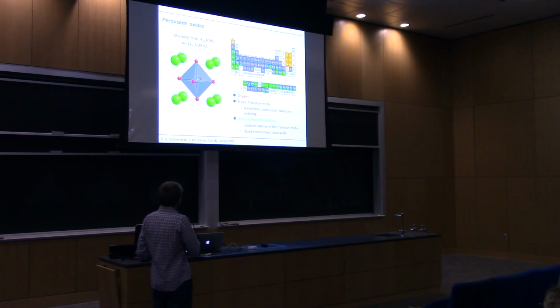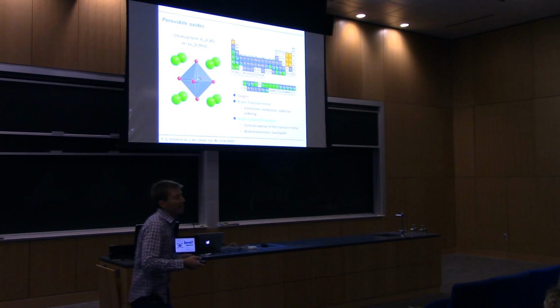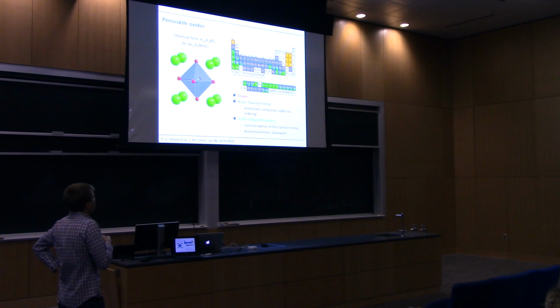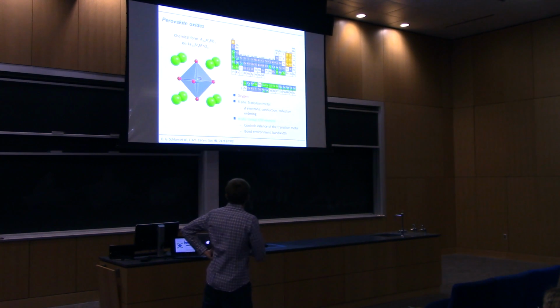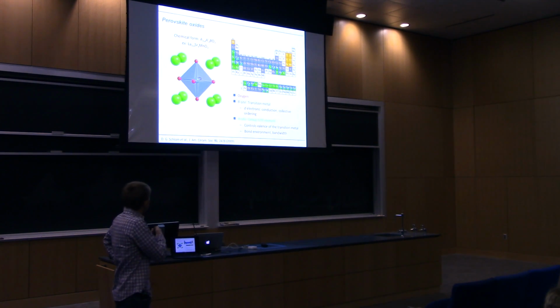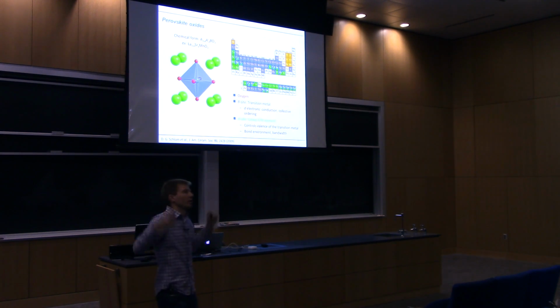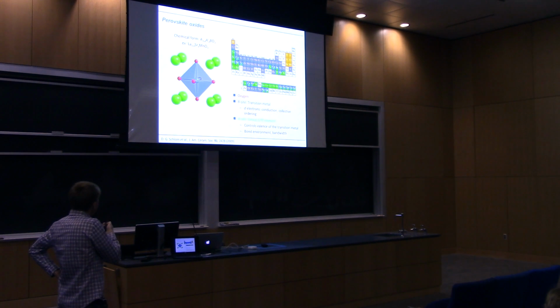It's these BO6 electronic states that reside near the Fermi level, so they are responsible for things like conduction. And it's also these B electrons that give rise to things like magnetism. So I get this BO6 octahedra, and you'll be hearing a lot about this. These form a corner-connected network, three-dimensional throughout the perovskite material. And residing on the corners are the A site cations.